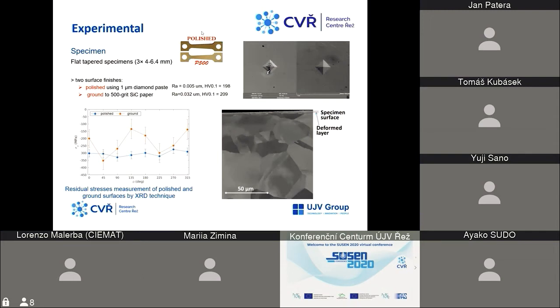Also, we use two surface finishes of the specimen. One is a polished laboratory finish using 1 micrometer diamond paste, and the other one is a ground surface, which was also ground in the laboratory up to 500 grit paper. We also measured the roughness and the microhardness of those surfaces, and also the residual stresses of both surfaces were measured by the XRD technique. Here you can see the results.